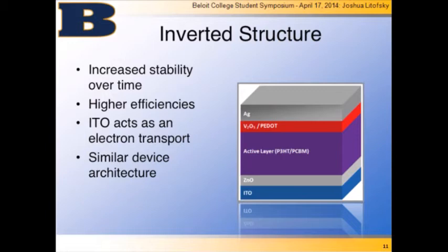It's over 99.9% nitrogen. And so I could take it out of the glove box, test it in the air, wait 10 minutes and test it again, and it may not work. It decays that quickly. The inverted structures last a little bit longer. Generally, they still work after about 30 minutes. Although that isn't good, it's still better than the less than 10 minutes that you get with the conventional cells.